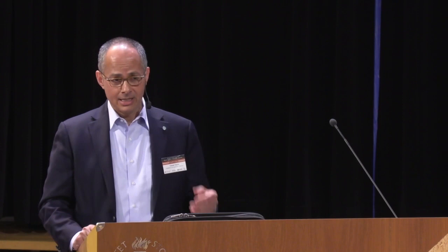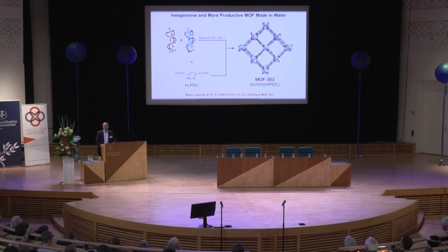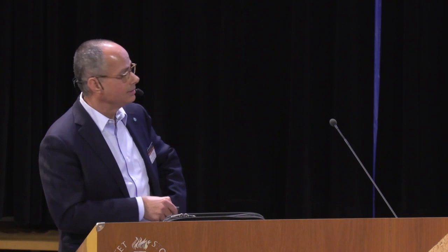Obviously we tested the water. It has absolutely no detectable amounts of metal, organic, or any other contaminant. Remember, the MOF is really its own filter — the water is evaporating, and there are several purification steps happening already. The MOF is selective towards water. Now, back to the power of chemistry — that was a zirconium MOF, and zirconium is $150 a kilo. If we want to use this on a global scale, we need a much cheaper metal. So reticular chemistry is now at work: you can make an aluminum compound — we call it MOF-303 — that works even better than the zirconium compound. Aluminum is dirt cheap, and this synthesis is done in water.